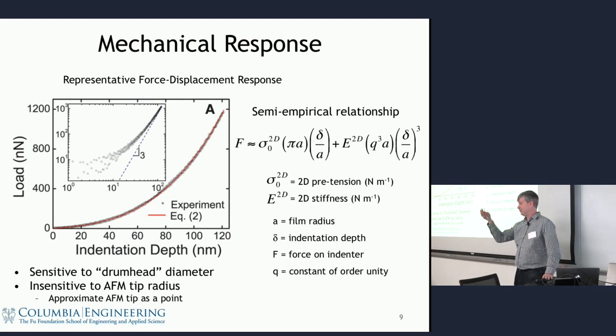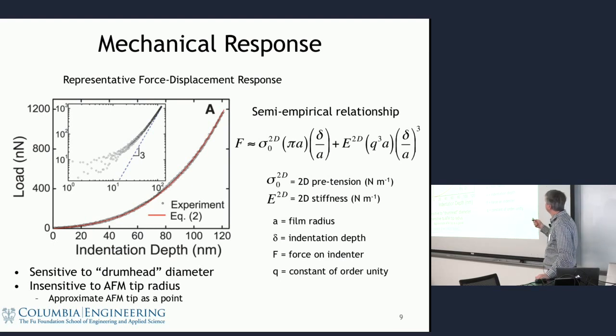And so in the end, when we do this 2T sine theta, which is 2T times the deflection, we get a linear and a cubic term. So this is a nonlinear response from still a linear mechanical response. We still have F equals kx, the linear form of Hooke's law, but because of the geometry, we have a nonlinear geometric response. And so the force in a 2D membrane, you get the analogous thing happening. The force goes like the built-in strain times the first power of the deflection, and then the Young's modulus times the third power of the deflection. So linear plus cubic term, and that's exactly what we see here.